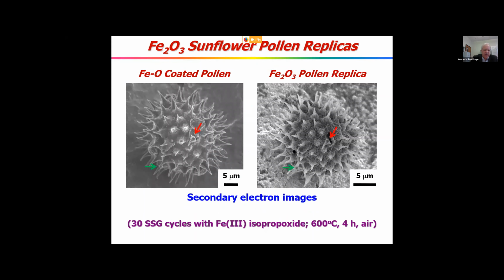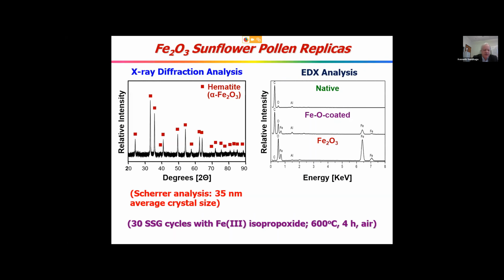On the left, you see again the iron oxide coated pollen. I've pointed a red arrow to show a cracked echinus and a green arrow to show a ball on the end of one. On the right, you see the same pollen particle now as hematite after firing, and again you see the cracked echinus and the one with the ball on the end, on the outside surface. This is made of hematite, which is weakly ferromagnetic.